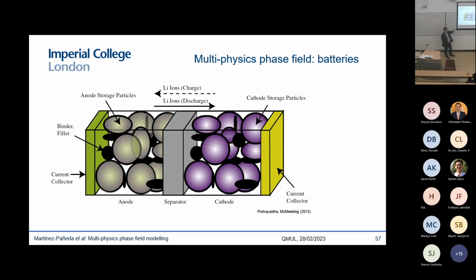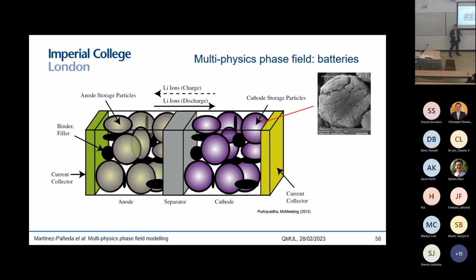What is happening here is that whenever you charge, you have lithium ions going from the cathode to the anode, and from the anode to the cathode when you discharge. During that lithiation, lithium is intercalating into these storage particles, causing mechanical strains and volumetric changes. This cyclic shrinking and swelling of the storage particles causes the nucleation and growth of cracks in those particles, and this is one of the mechanisms that is degrading battery performance.